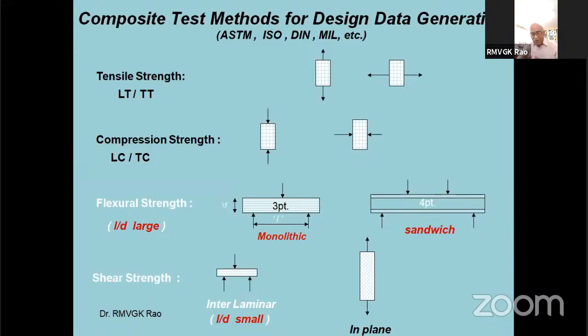In metals, actually, 3 or 5 specimens are okay. That is approved because metal is highly homogeneous and repeatable. But in composites, you have to do at least 15 or 20 or sometimes 30 for every batch, and the variability will be so much that you neglect the top 5 or 10 and bottom 5 or 10, that means the highest and lowest values, and take only the middle 7 or 8 values closest to one another within a certain tolerance. Then you take an arithmetic average, and then do a statistical average on a large number of batches of specimens. In fact, it is not a hype if I say we have tested thousands and thousands of composite specimens only to generate one single property, one allowable, a tensile allowable, or whatever it is. So the important point is now you generate the data.